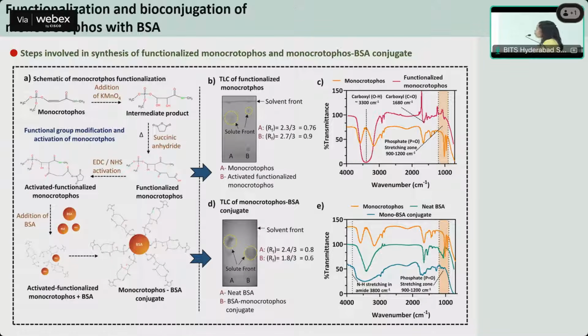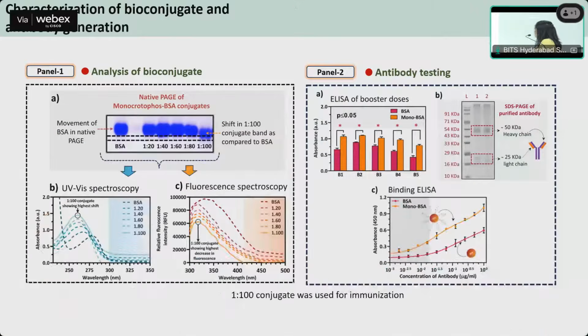Then it was linked with the carrier protein to make it immunogenic. Further analysis was carried out by TLC and FTIR to validate the synthesis. Then different molar ratios of this conjugate with monocrotophos were prepared, where we observed that 1:100 was quite good enough, and we could also see the redshift in the UV spectra and the decrease in fluorescence intensity, which suggests the successful synthesis of the conjugate.